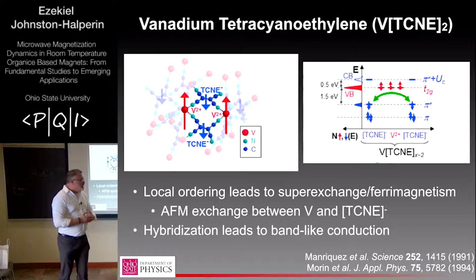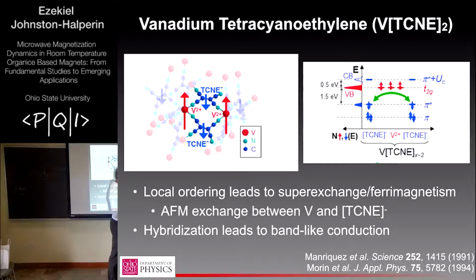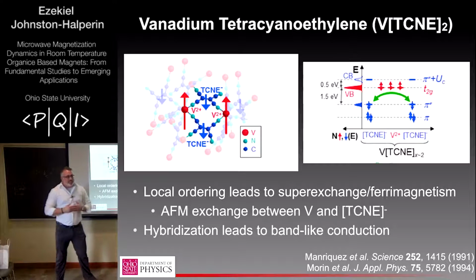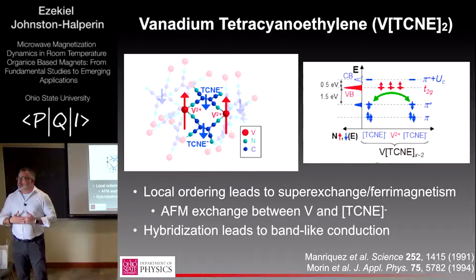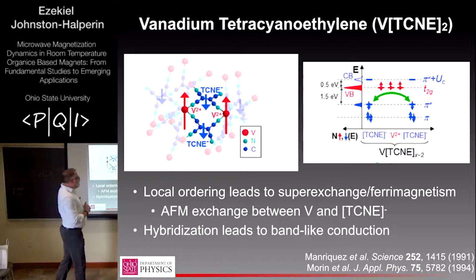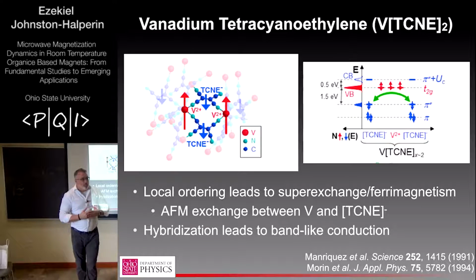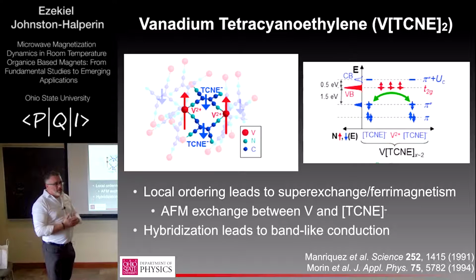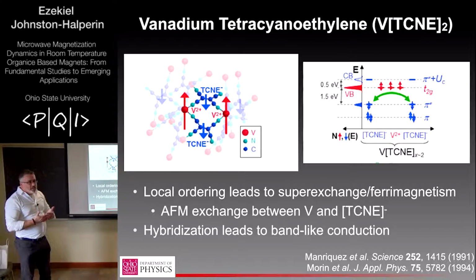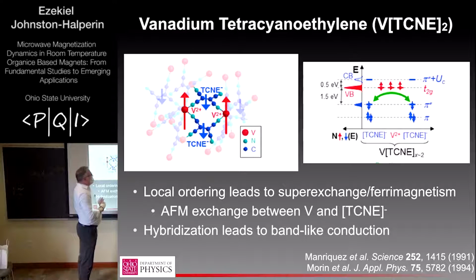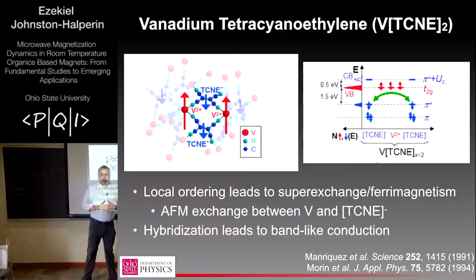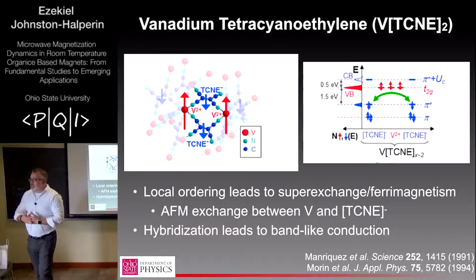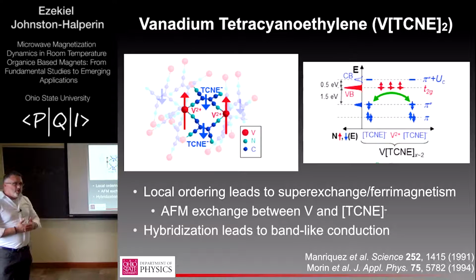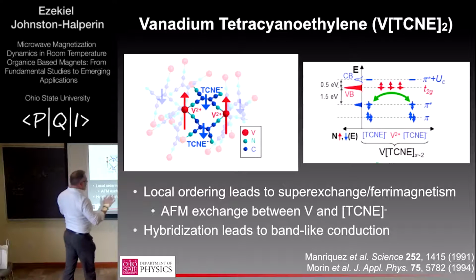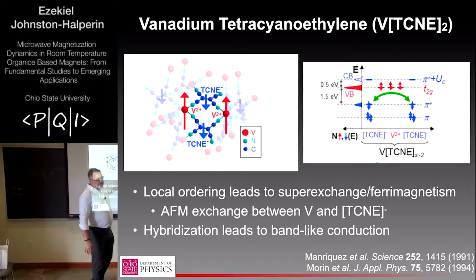I don't know. This is not a model we developed. This comes out of these references. So I can tell you that this math of getting one Bohr magneton per formula unit to within the experimental accuracy is borne out. So if there's symmetry breaking here, it's not suppressing the magnetic ordering. I will say, in my opinion, the charge transport in this material is not well understood.